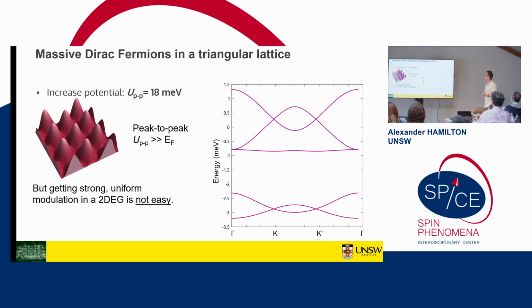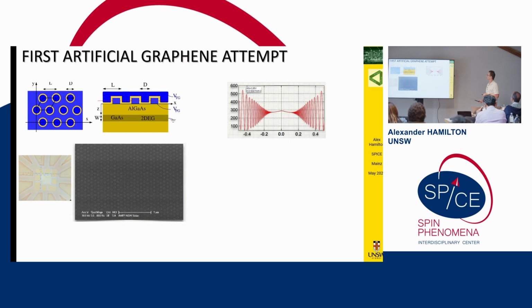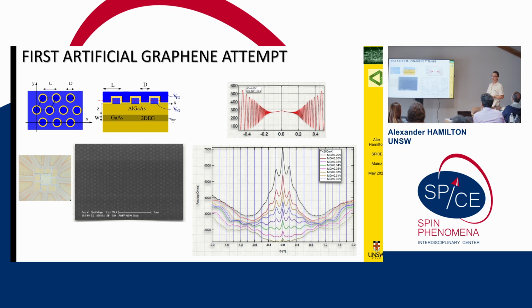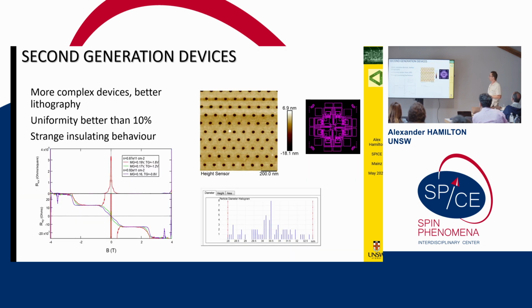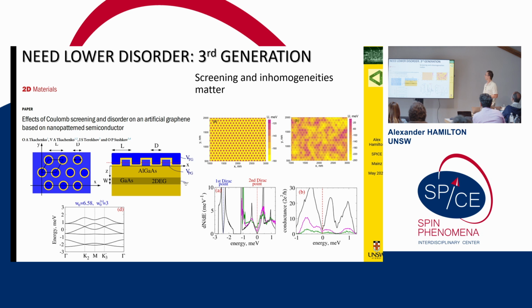So this was 6 years ago. This was our first generation of samples, and they were just too disordered. 4 years ago, this was our second generation of samples. We got the uniformity of the lattice, really improved it. They were still too disordered. You're really susceptible to disorder. We did a lot of numerical calculations to show how disorder hurts.